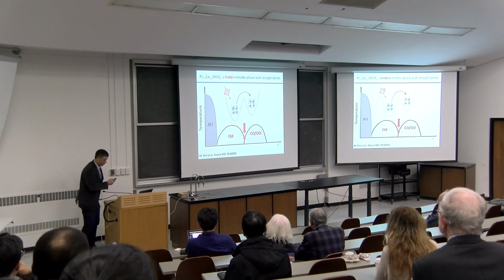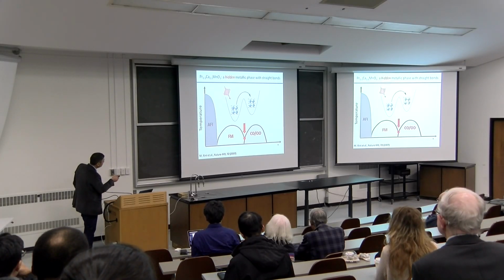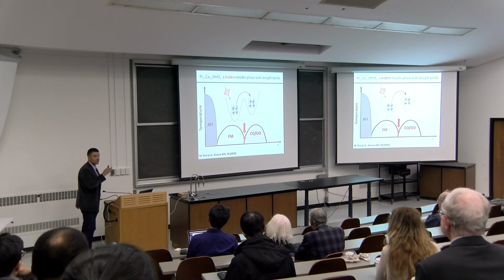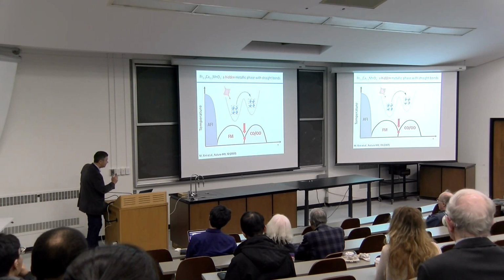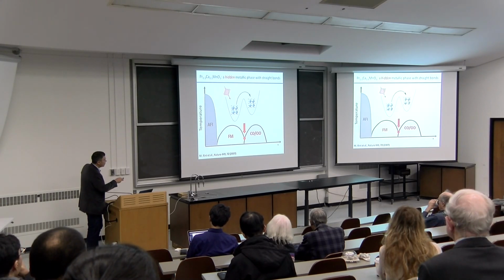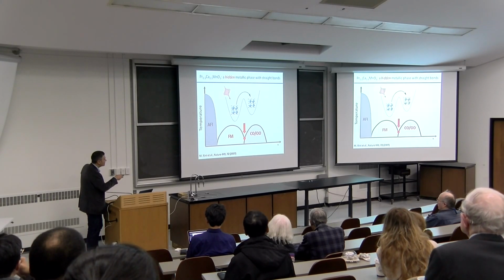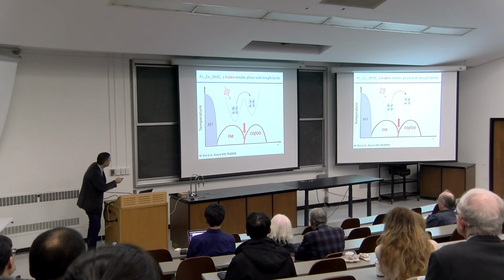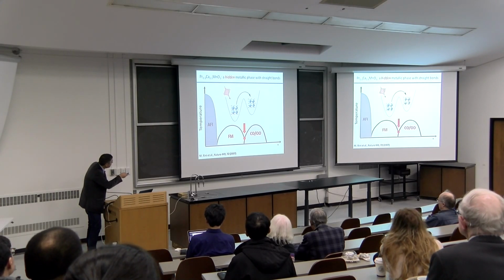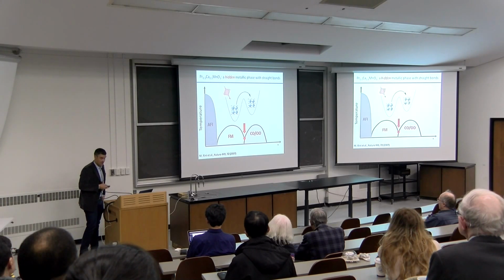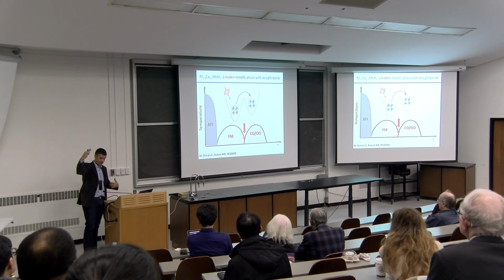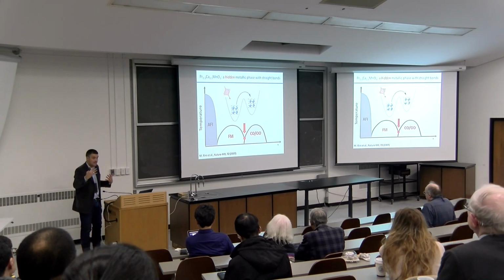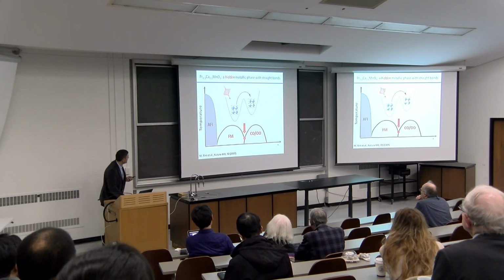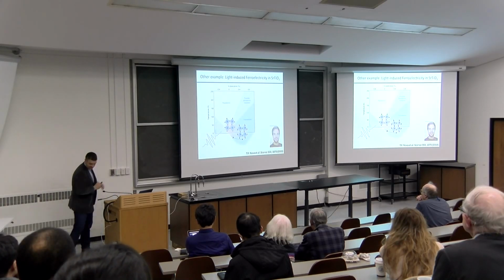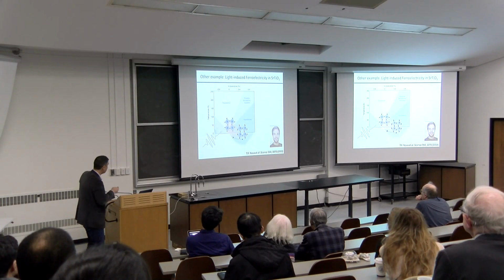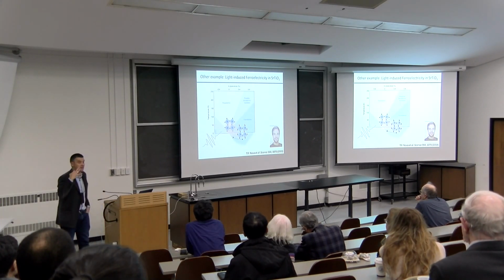One example is, for example, some manganites, in which one can, these are the so-called colossal magnetoresistive manganites, and I won't tell you too much about them, but I can only tell you that in some of these materials, by changing the bond angle by only a few degrees, one can change the conductivity by, say, 7 orders of magnitude. There's hidden phases that one can access, for example, by pressure or by other forms of stimulation. And we showed that by pumping a phonon in a system that has a 2 eV gap, I could create a phase that is not thermally accessible, which becomes a metal. So that's one example. Another example, again, just flashing this here, is recent work by my student who's just graduated now, Tobianova, who has taken strontium titanate, a known incipient ferroelectric.